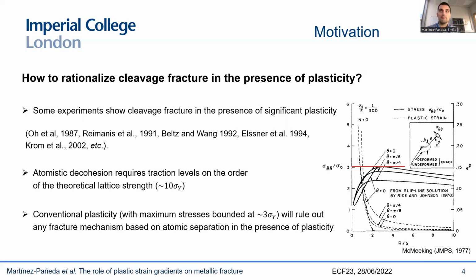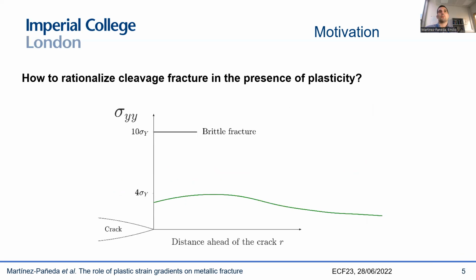And I mean, we know this going back almost 40 years now, right? Thinking of the work of Bob McMeeking. Bob McMeeking, during his PhD thesis, was the first to simulate using finite element analysis what would be the stress fields that are predicted ahead of a crack, taking into account large strains. And as you can see, this is taken from one of his earlier papers. The maximum stress level that you get ahead of your crack is 3 times the yield stress. So we're very far away from those 10 times yield stress requirements that are needed to achieve the cleavage strength. And this, of course, can change a little bit, whether you have a bit of hardening in your material. It may be that your maximum stress is 4 times the yield stress, but still you're very far away. So this is basically our conundrum.